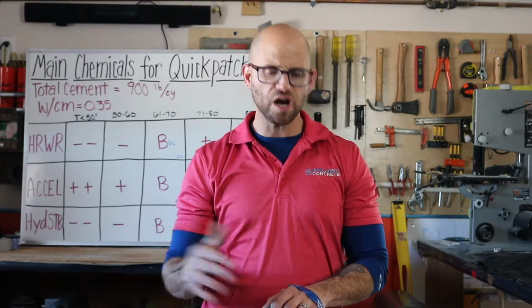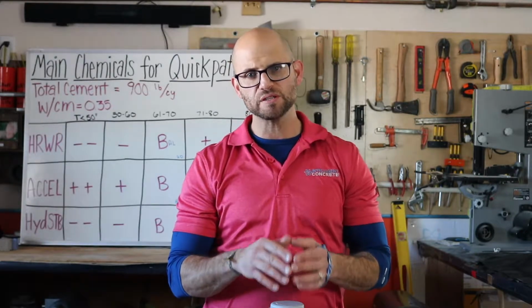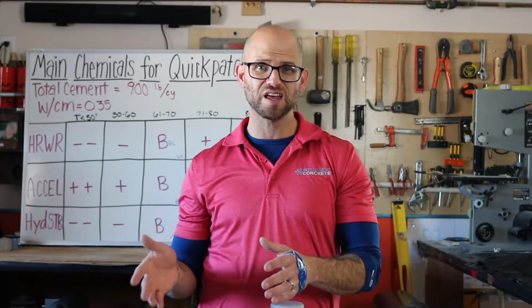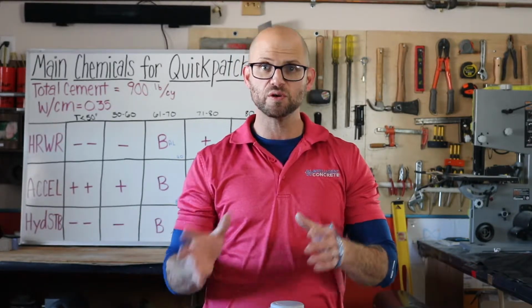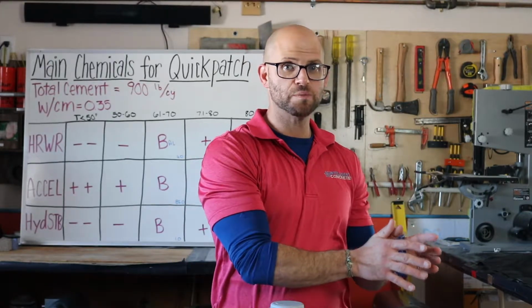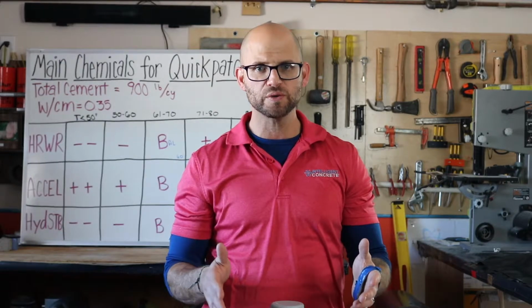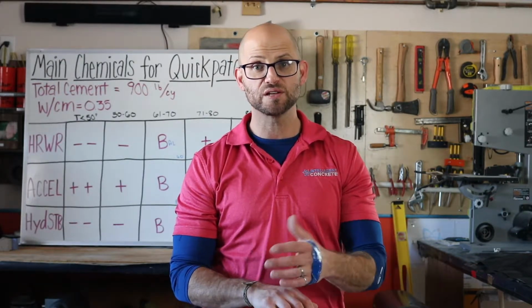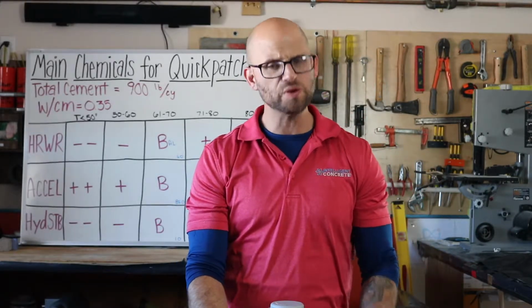So the concept that I'm talking about is retaining that workability with a 90-minute window, and then a short period of time after that, somewhere between 4 and 12 hours, you develop that strength. So the same as the fast track pavement of old, but now we're controlling that workability window and giving folks time to actually place it, finish, and close up that surface.